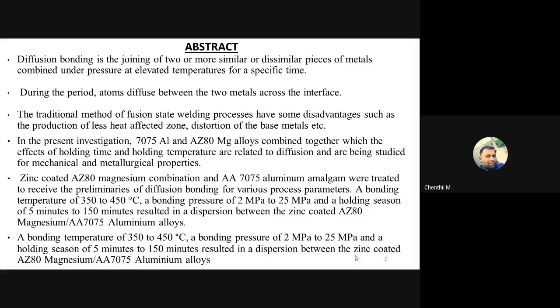Here in this investigation, we used a 7 series aluminum alloy, AA7075, and a magnesium alloy, AZ80, combined with respect to the effect of holding time and holding temperature on diffusion. The mechanical and metallurgical properties were studied. Zinc coated magnesium and AA7075 aluminum alloy were treated under diffusion bonding. Temperatures were taken from 350 to 450 degrees Celsius, pressures from 2 megapascal to 25 megapascal, and holding times from about 5 minutes to 150 minutes, between the zinc coated AZ80 magnesium and AA7075 aluminum.